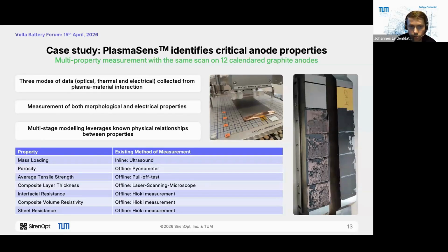We have multiple measurements, as you can see in the table on the left bottom side. We measured, as I've said, the mass loading inline with an ultrasound system, and then we have the porosity, which is measured offline with a pycnometer. The average tensile strength, composite layer thickness, interfacial resistance, and the resistivity of the composite volume. So in total, we have multiple measurements of our samples.